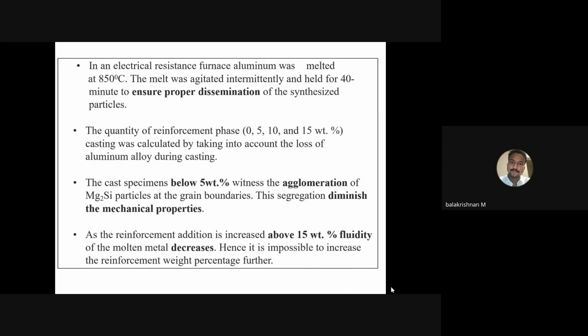Then, if in case the reinforcement weight percentage exceeds 15 percentage, what will happen? Automatically, it will reduce the fluidity of molten material. Automatically, during the casting process, the threshold value and solidification will be affected. Due to that, the microstructure changes will not happen. That's why I limited that to 15 percentage. The minimum value is 5, the maximum is 15.